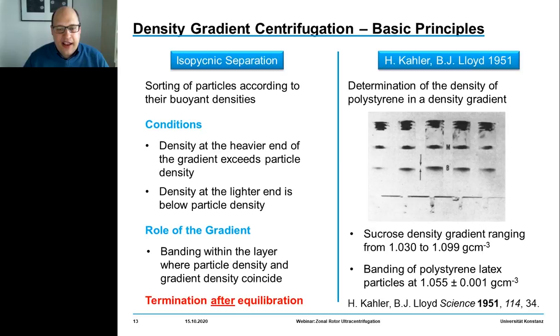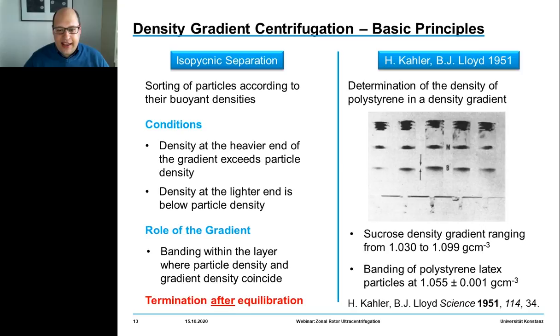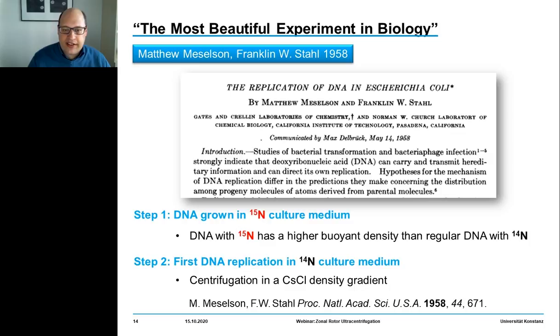This provides really excellent resolutions. You need to build density gradients where the lower end has lower densities than the actual density of the particles, whereas at the heavy end of the gradient the density exceeds the buoyant density. This is an equilibrium technique and you get banding in discrete zones according to buoyant density.